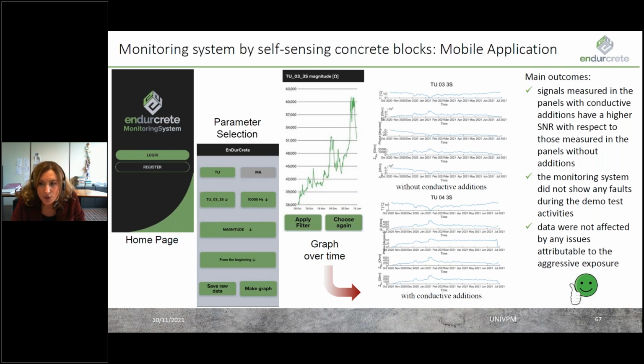Results related to the data acquired for approximately 10 months confirm that the signals measured in the panels with conductive additions have a higher signal-to-noise ratio with respect to those measured in the panels without additions, confirming the results obtained at lab scale. The low-cost monitoring system did not show any faults during the demo test activities, and finally, data were not affected by any issues due to the aggressive exposure.